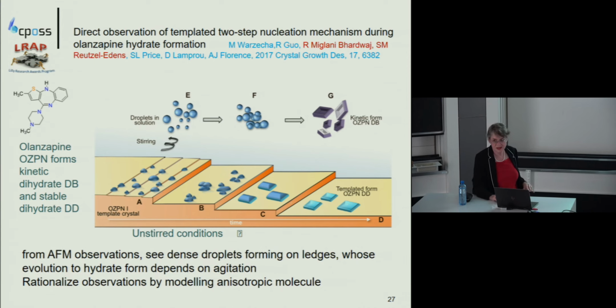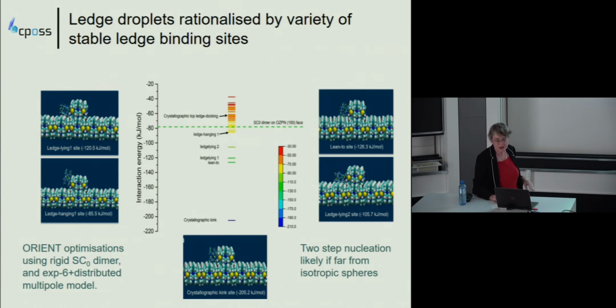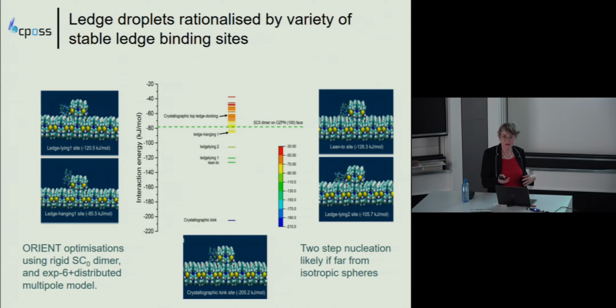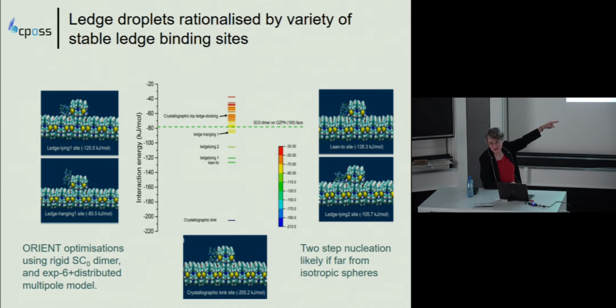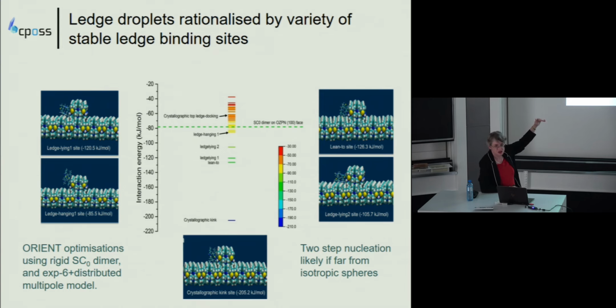So we had to look at that, and this has some information about modelling. First of all, why are we seeing these dense hillocks by the ledges? Well, we tried building a model for the ledges and just letting the olanzapine dimer dock onto it. Obviously, the lowest energy site is carrying on the crystal structure in the ledge site. But there are an awful lot of other structures where the dimer will stick in a low energy minimum that are lower in energy than it going down onto the surface there. So it's not surprising that in the dissolution of the olanzapine and the nucleation of the dihydrate, you're getting these blobs, that it's very difficult to orient the molecule in the process of nucleation there.